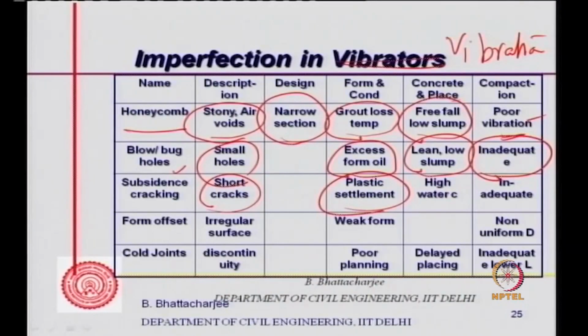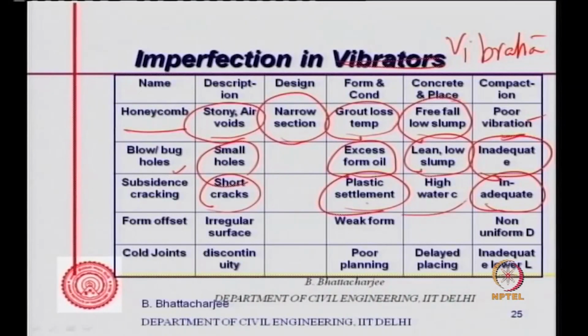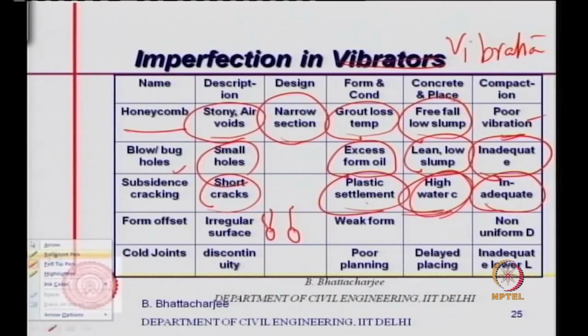Now it's a bleeding concrete. This can occur in concrete which is bleeding, because the water comes up and the solid subsides. So this can happen, and inadequate vibration can result in this. High water content is usually the cause. So in concrete which has got high water content, you might get short cracks. The cracks look like this, in fact. Sometime we might be discussing over reinforcement, sometime you might see, just over the reinforcement, the top concrete surface might look like this. There is a crack, and then there is a subsidence, there is a crack, and so on and so forth.